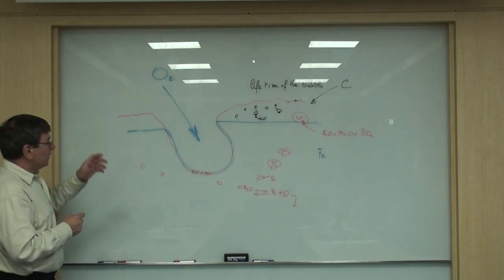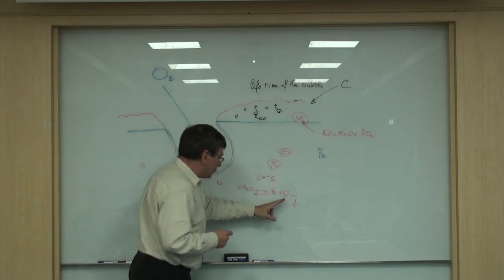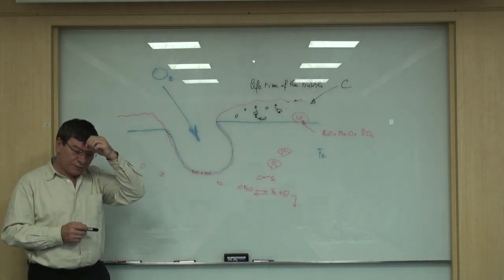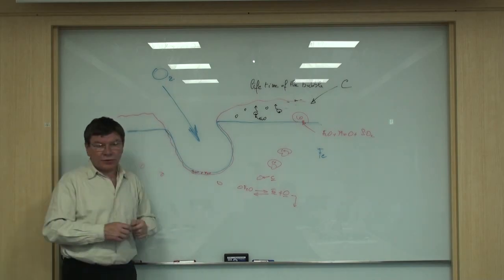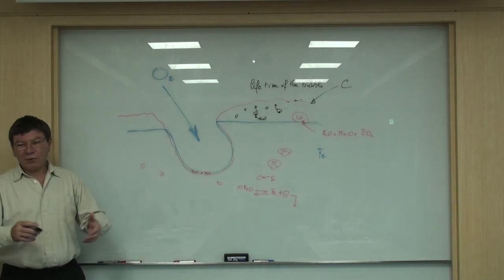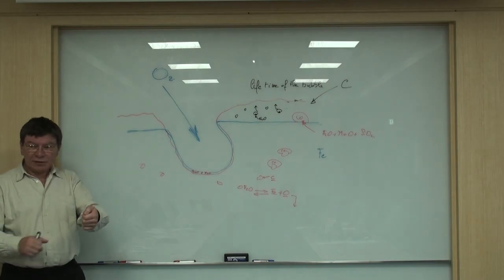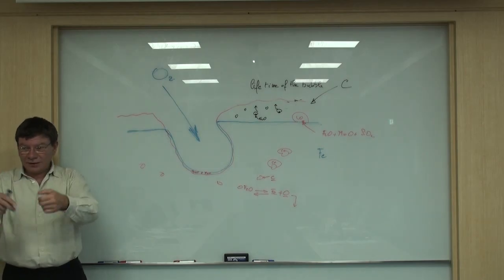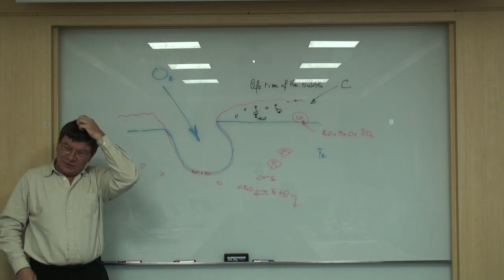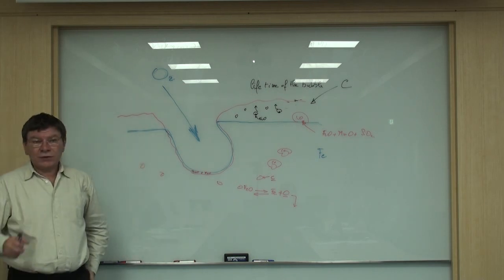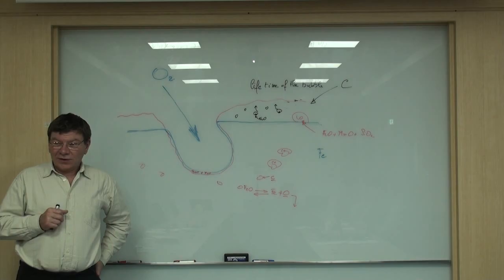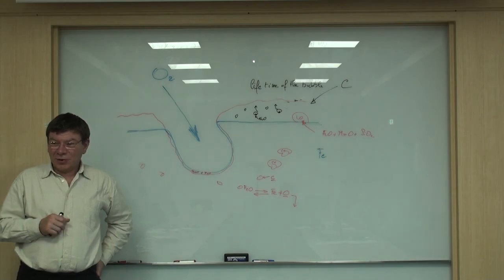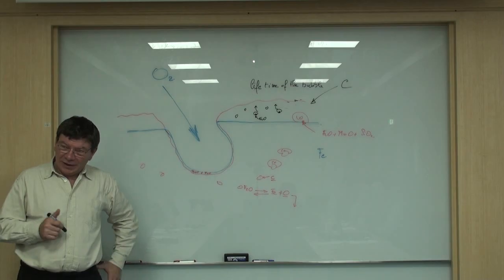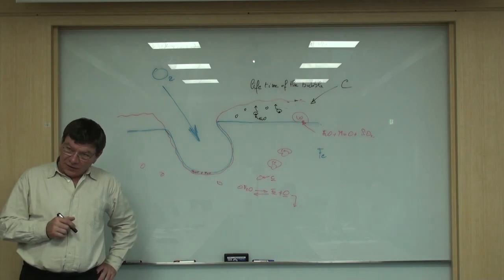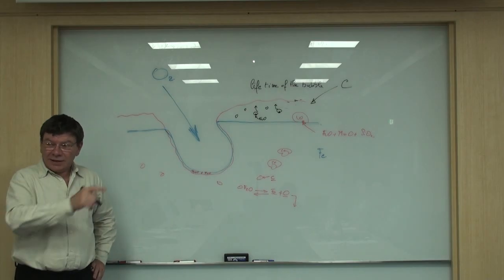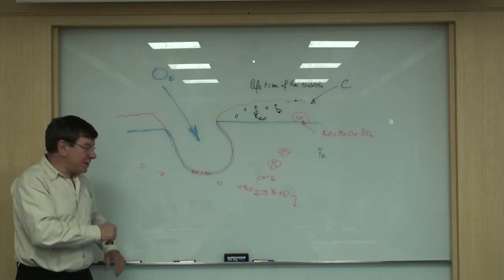So this is for the foaming slag. Now what happens to the dissolved oxygen? You have seen already boiling water. You take a pan, you put water on the gas, and the water starts to boil. And you look into the pan, what do you see? What do you see when you observe the water boiling? Bubbles are generated from the surface of the pan. Exactly. And it's exactly the same for the decarburization.